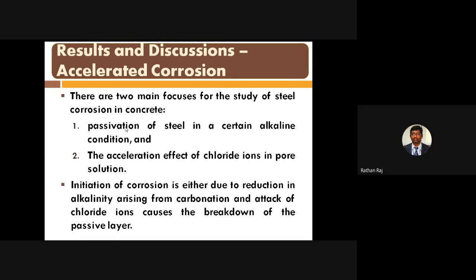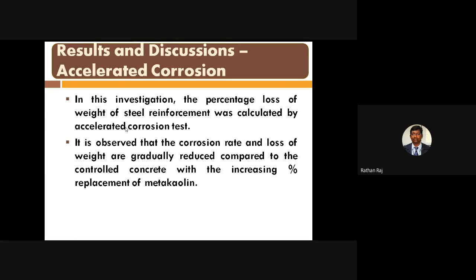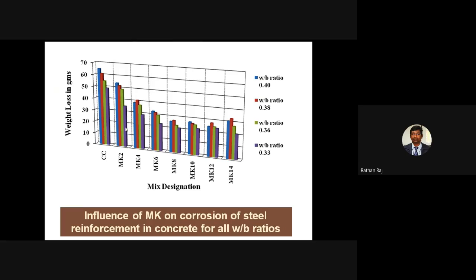So here, the initiation of the corrosion is only because of the reduction in the alkalinity, arising from the carbonation and the attack of the chloride ions, which causes the breakdown of the passive layer. So in this investigation, the percentage loss of weight of the steel reinforcement was calculated by accelerated corrosion. So let me go to the figure.